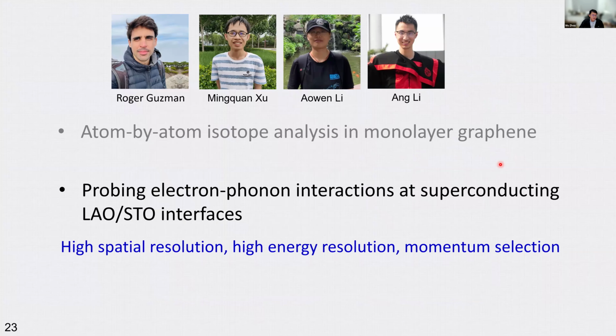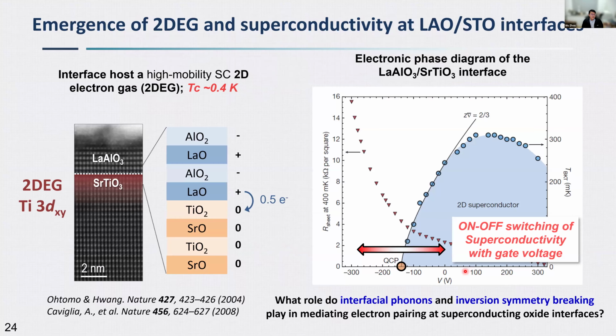And the second example I'm going to show you is going to use, again, the high spatial resolution and high energy resolution, but combined with momentum selection during the experiment to understand electron-phonon coupling in a superconducting oxide interface. So the system is very different from the previous example. In this case, it's an insulating oxide, lanthanum aluminate, growing on top of strontium titanate.